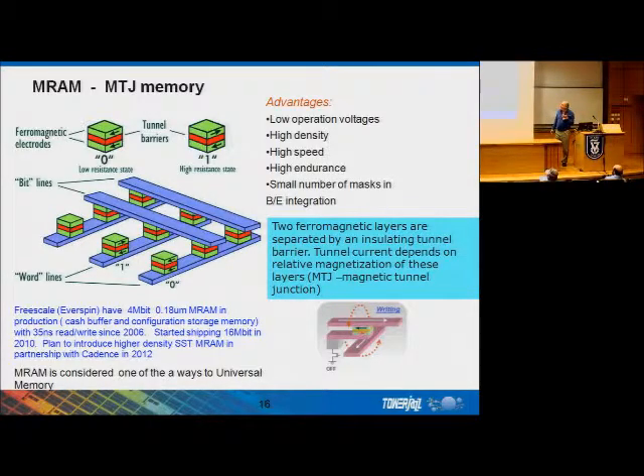And the last message is about the MRAM. Our company is developing MRAM with Crocus technology. MRAM, magnetic resistive memory, is also from the field of resistive memory. The principle is absolutely different. The principle is changing the resistance of the magnetic tunnel junction, where there are two vectors in the top and bottom layers. Depending on the polarization of the top and bottom layers, you can get different resistances. This memory has practically the same advantages as the other types of resistive RAMs: low operation voltages, high densities, and so on.